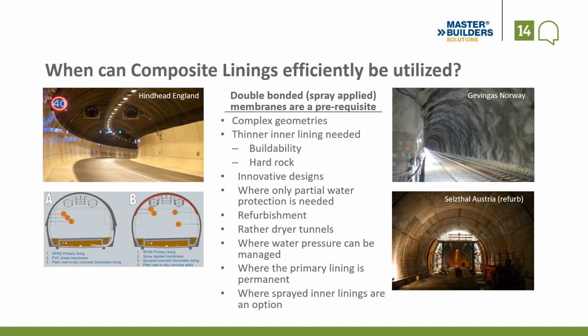Hard rock, that's obvious. In hard rock you can follow the contour with your 50, 100 millimeter. You leave an undulated surface. If you want waterproofing, follow the contour with a spray applied membrane, easy, and then cover it again. That's obvious. Innovative designs, that's here, sprayed final lining, and cast sidewalls for the reflection and cleaning. Super. And to be very fair, if it's really wet in your tunnel, don't consider it. You can treat the water, but if it's too much water, it's useless. It works, but it's not worth the effort.